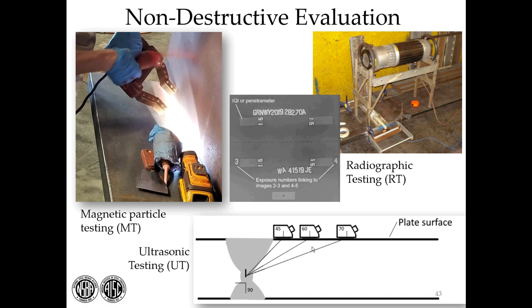The nice thing about this method versus RT is that with basic geometry, you can tell how deep your discontinuity is. In this particular weld, you can't look at it and tell how thick it is, although based on the penetrometer, you know it's a rather thin piece, it's a rather thin plate. This is actually a web. But just looking at this, you can't tell how thick it is or how deep those discontinuities are.